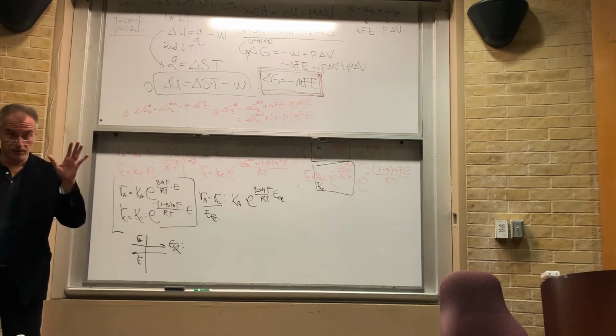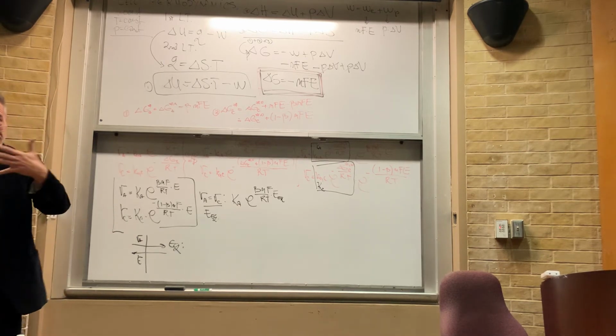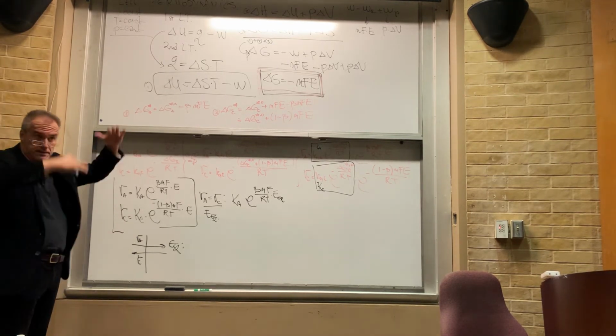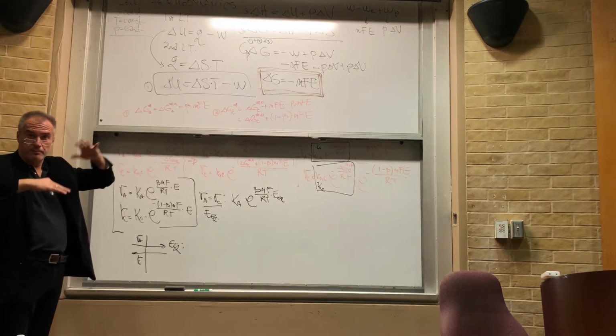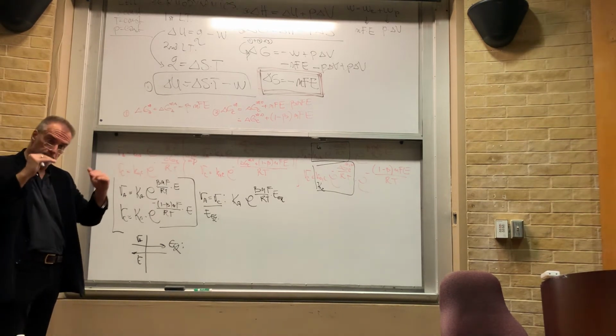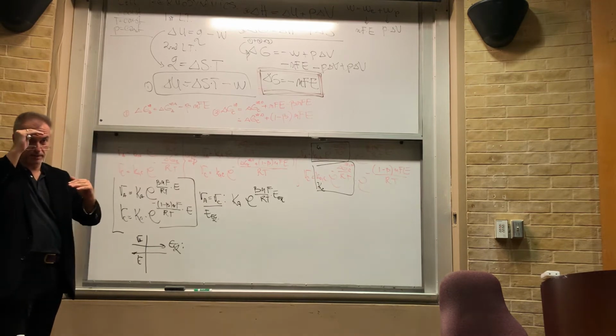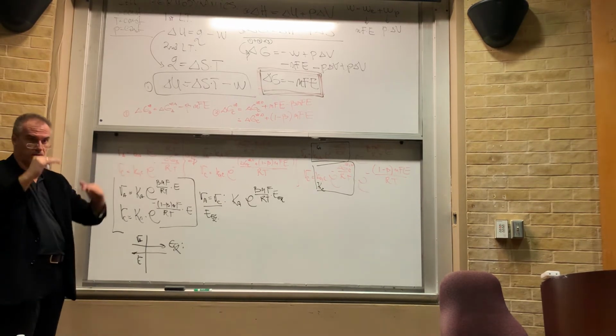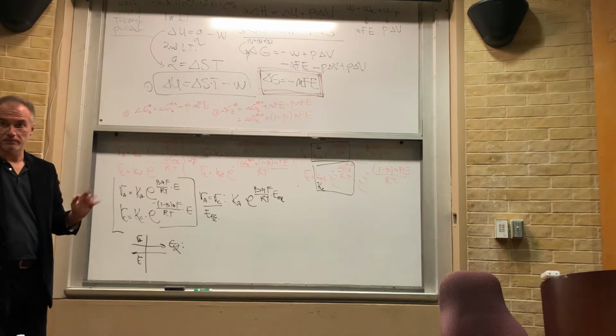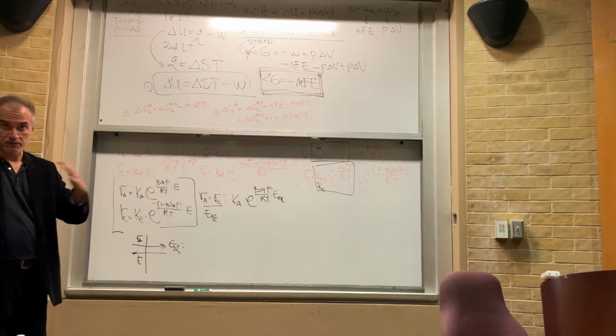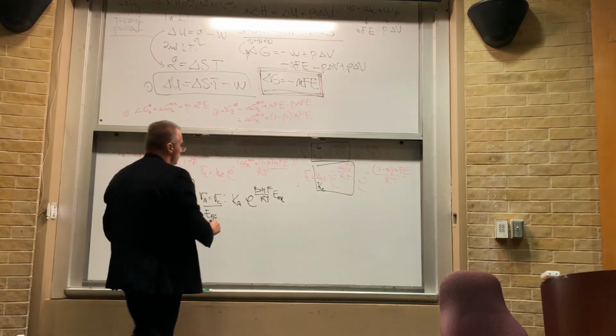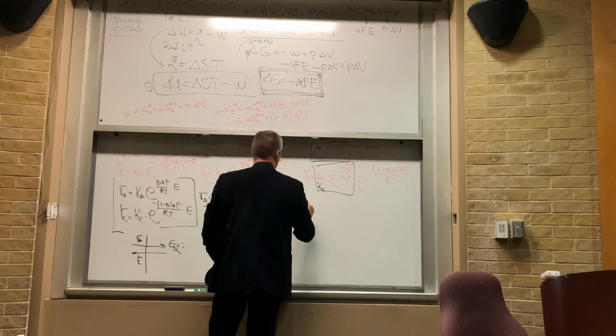It's not any potential. At a particular potential, I bring these two rates to be equal, because I can modify the whole diagram by adding one or another potential, bringing down, bringing up, until ΔG is equal to zero. Basically, that's the idea of the whole process, right? And so that means that this is equal to K_C e to the minus (1 minus β)nF E equilibrium potential over RT.